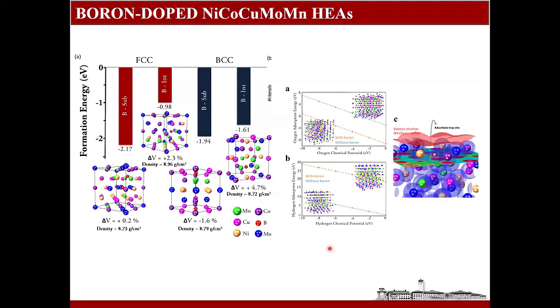So we also worked with a computational group, and they did some computational analysis for us. The substituted boron decreases the formation energy of the high entropy alloy. So this is for the FCC structure. This is showing that the substituted boron is more stable than the boron going into the interstitial sites. So we have the same observation for the BCC structure as well.